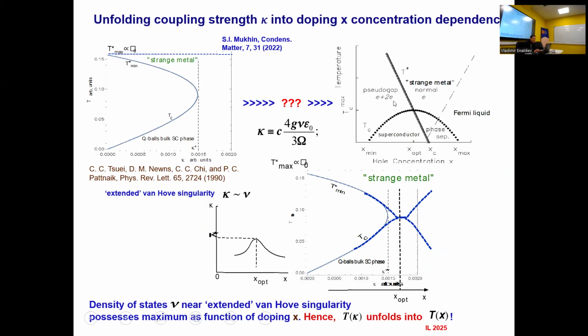The reason could be very simple, because here what we have on the horizontal axis is this coupling strength at the nesting region of the Fermi surface. Now, if you consider, for example, extended Van Hove singularity, then this coupling strength as a function of doping has a maximum.